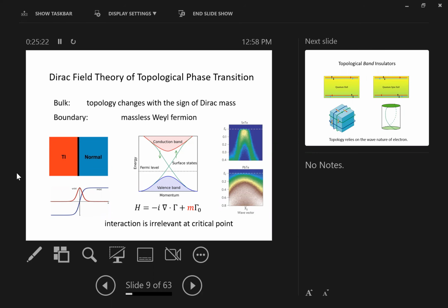And back to the case of lead telluride and tin telluride. As I said, lead telluride should be topologically trivial, so it should have no surface states on the boundary. And indeed, this is what photoemission observed. There are no states at the Fermi level. But tin telluride is topologically non-trivial, so it has to have boundary states. And you see from photoemission, there are states with this linear dispersion showing up at the Fermi level. These are two-dimensional surface states.